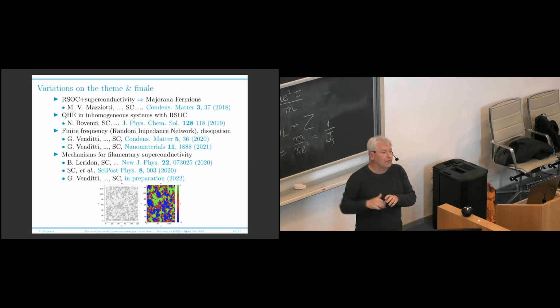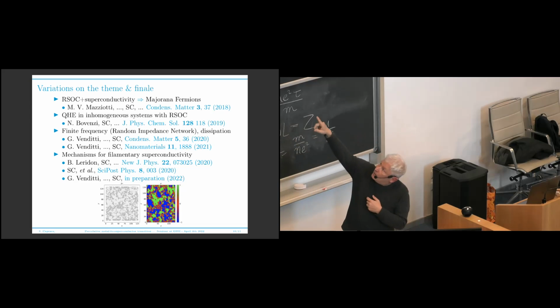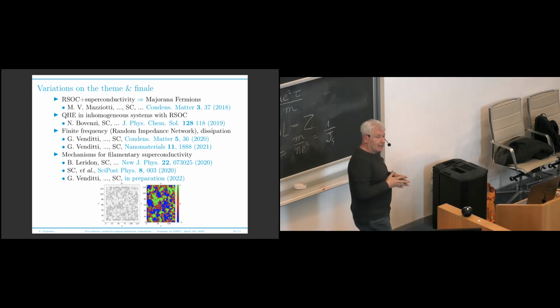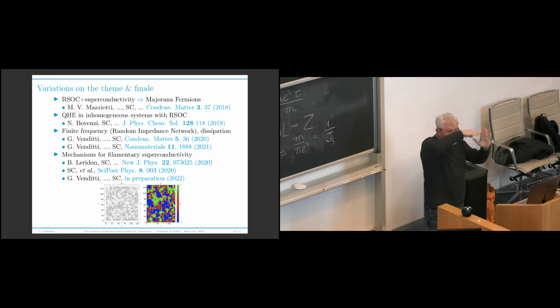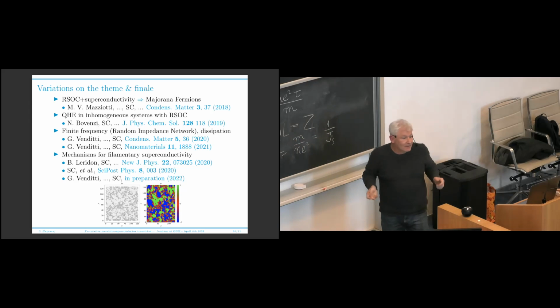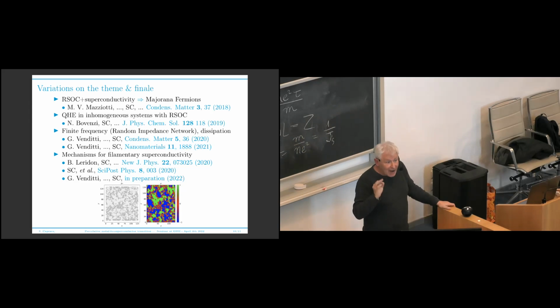We measure the superfluid response of our system with Monte Carlo, and we find that the superfluid response is finite. Whenever you have percolation of the red domains, you have superconductivity in the ground state, because now you have a percolating superconducting path in your system. So you have a finite superfluid stiffness in your system.